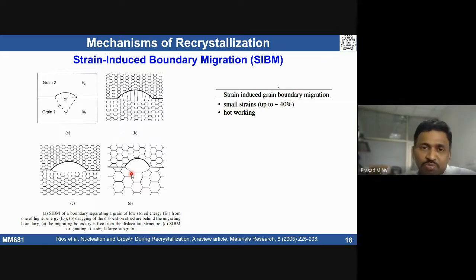There are various mechanisms people have put forward, but the well-known ones I have given are: first, subgrain formation followed by subgrain boundary migration. The second one, subgrain formation, rotation, and coalescence. The third one, strain-induced boundary migration, which was developed later than those two mechanisms, and has been widely accepted as a mechanism during hot working.